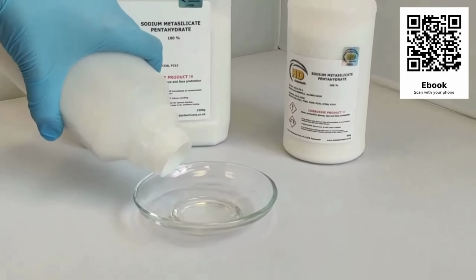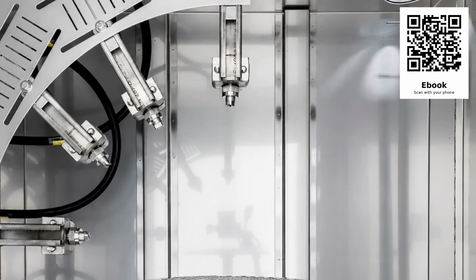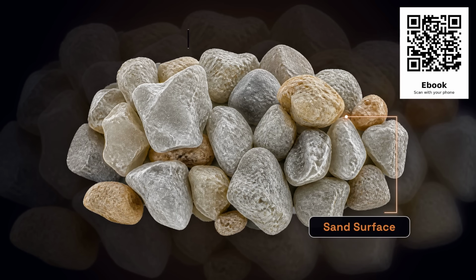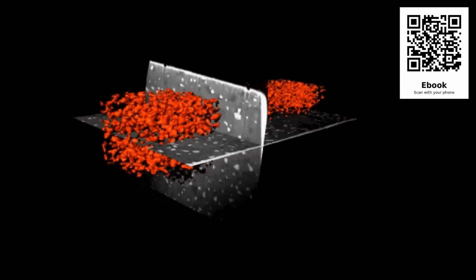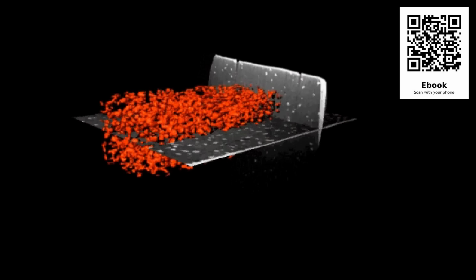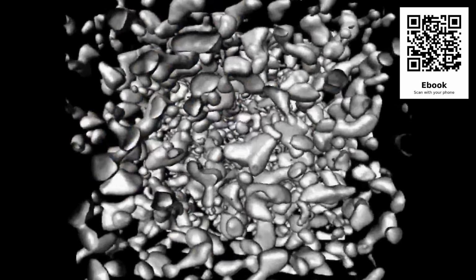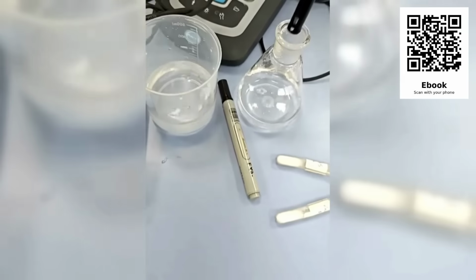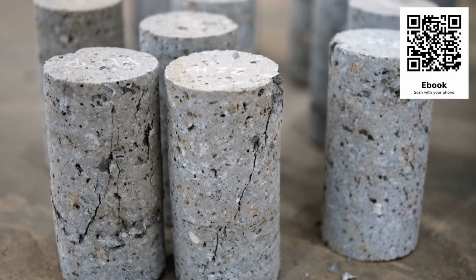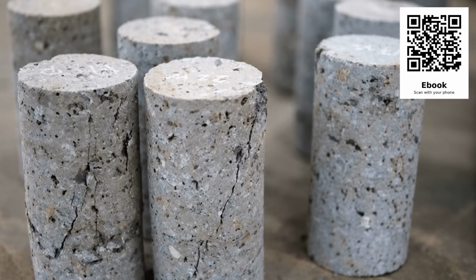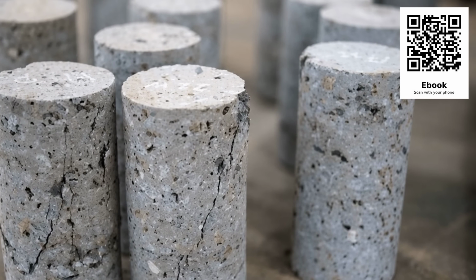Sodium silicate works differently. When you mix sodium silicate solution with sand and allow it to cure in the presence of carbon dioxide from the air, or with the addition of a setting agent like calcium chloride or sodium bicarbonate, the silicate polymerizes. The silicon-oxygen bonds in the silicate solution link up with the silicon-oxygen bonds in the surface of each grain of sand, forming a continuous, three-dimensional silica network. The sodium is left behind as a soluble byproduct, which can be rinsed out or simply allowed to weather out over the first few months of the material's life.